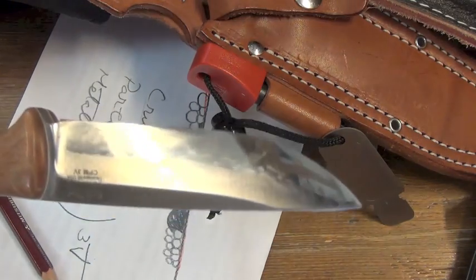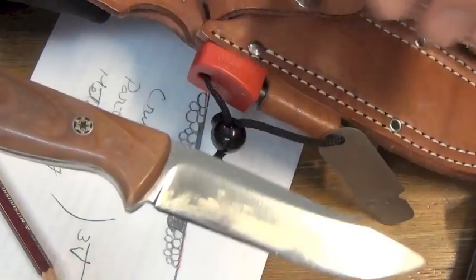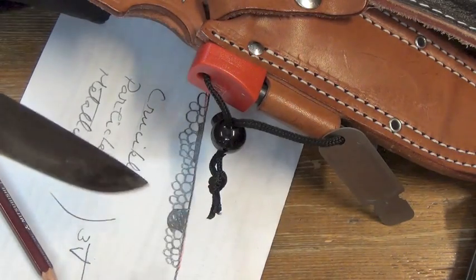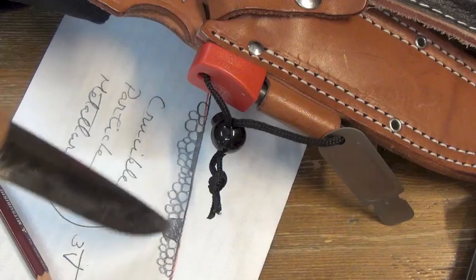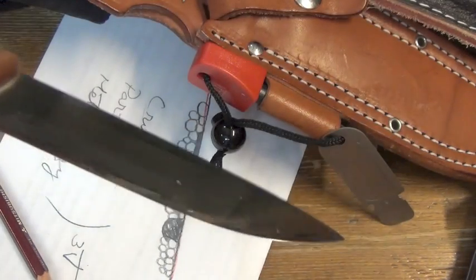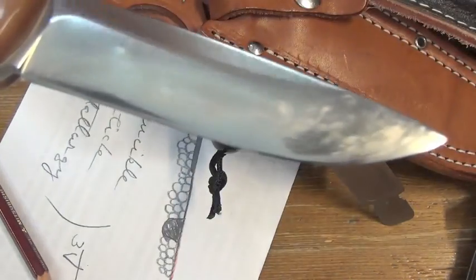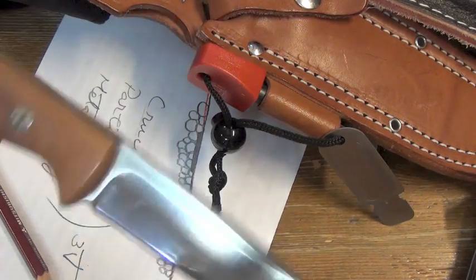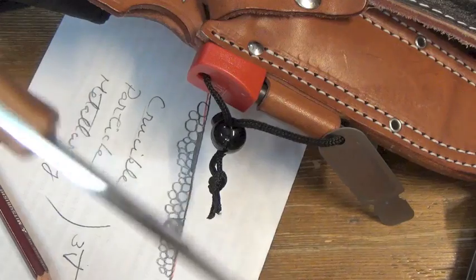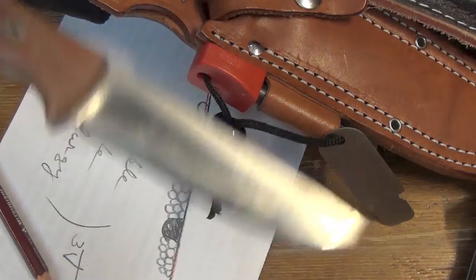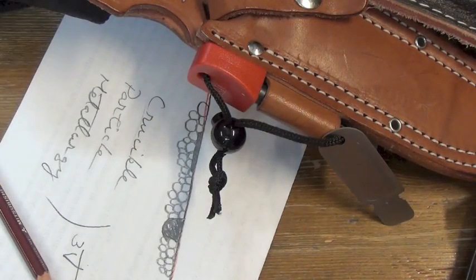I sharpened to make 30 degree angle. It took this kind of microchips, many many. And I now made my asymmetric blade typical geometry: this side convex, this side flat. I estimate this angle is 30 and a bit, a bit larger than 30. Then I expect this will hold very, very long.